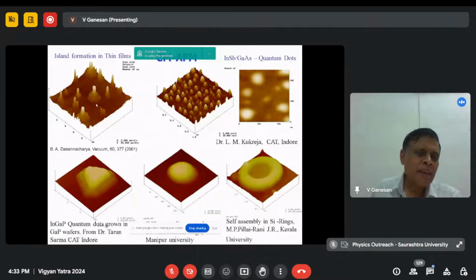So when you are coating a metallic film on an insulating substrate, they first start as small islands of metallic clusters. These islands will slowly grow, swelling, and finally they come and touch each other in percolation. So you see initially non-metallic conduction, followed by metallic conduction. You can do it in silver films very easily. One of our former directors was interested to do this in our own laboratory where we were setting up a thin film unit, and we did it for silver films.